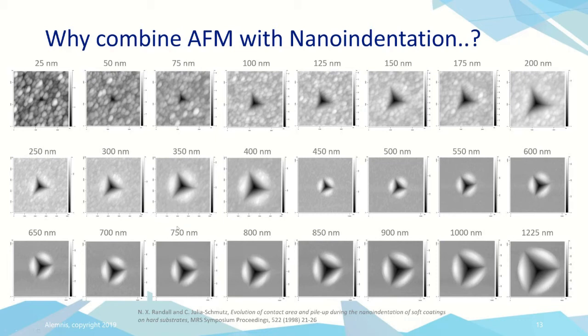We can also see how good the AFM is at telling us the surface roughness. So for example, at very shallow depths, we can see that the indentation size is basically the same order of magnitude as the surface roughness. So therefore, we're not going to have a very good contact between our indenter and the material itself.